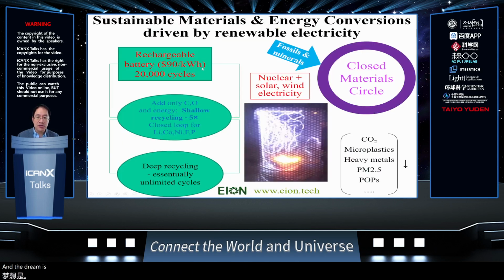And the dream is to have very cheap battery, less than $90 per kilowatt-hour system level, and which can cycle, let's say 20,000 cycles. So that's the cell. And then by doing shallow recycling, we can recycle it 5 times with a completely closed loop for lithium, nickel, cobalt, and all these fluorine and phosphorus elements. So nothing gets discharged to the environment. And by using this kind of recycling combined with solar, wind, and nuclear baseload, we can have a completely electrified economy where we basically do not emit anything, CO2, microplastic, heavy metal, all of these in a closed loop. So that's sort of the ultimate dream. And I'm now involved in a company called E-Ion that's developing this kind of recycling technologies.